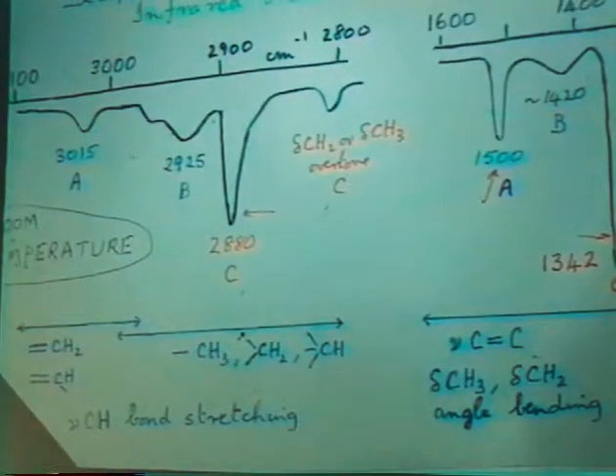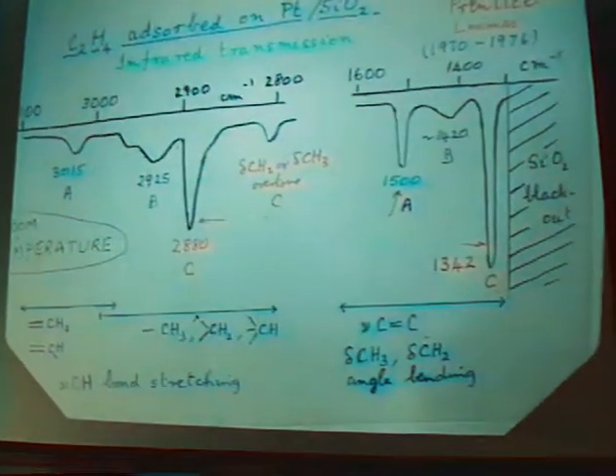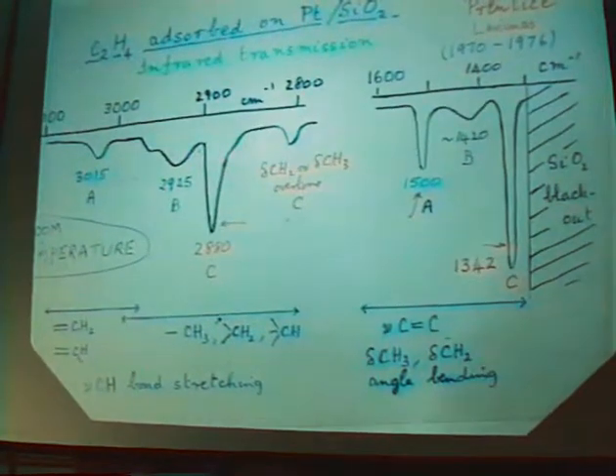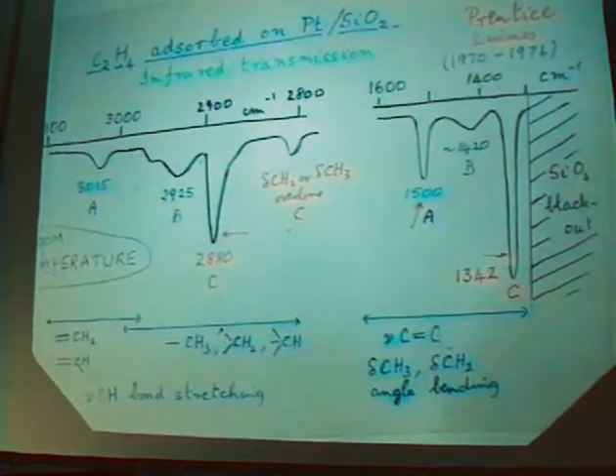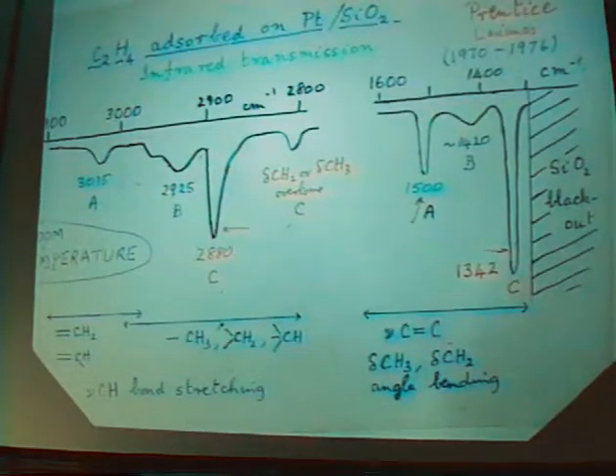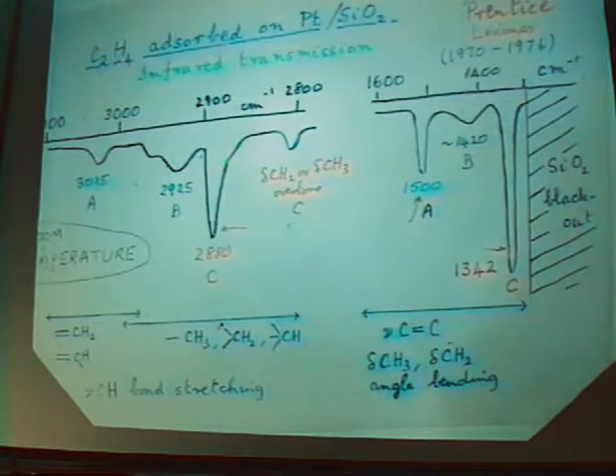We did what sometimes people refer to as one experiment too many. We put ethylene on the surface, and then we added post-adsorbed CO. And the result was that this band moved about 10 wave numbers, and this one virtually disappeared. So for a long while, we thought that these two strongest features were from different species. Well, later on, as you'll learn, we were able to correct that.